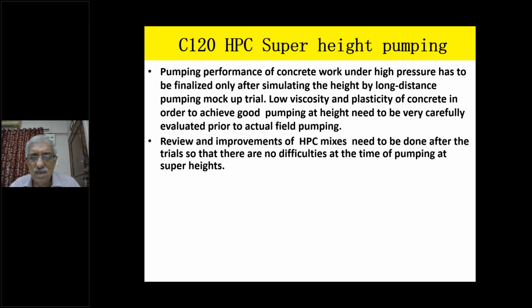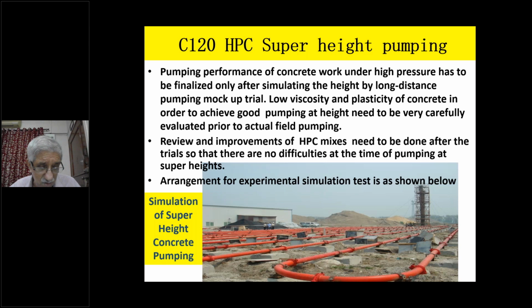Low viscosity and plasticity of concrete in order to achieve good pumping at height need to be carefully evaluated prior to actual field pumping. This is very, very important, and see how they do the simulation. Instead of putting a pipe vertically up, they have lots of bends and horizontal length of pipe, which is equivalent to the height of the building.